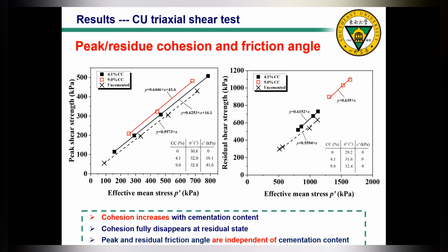Then from the CU triaxial shear test, we also use Mohr-Coulomb theory to get the peak and the residual cohesion and friction angle. The left-hand side graph shows the peak state, and the right-hand side picture shows the residual state. From this one, we can see that the red one represents the high cementation level case. The solid black one represents the low cementation level case, and the dotted one shows the uncemented case.